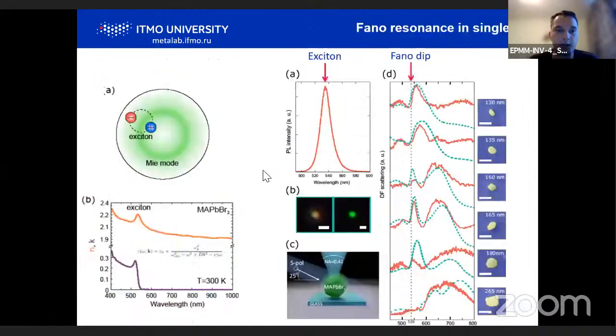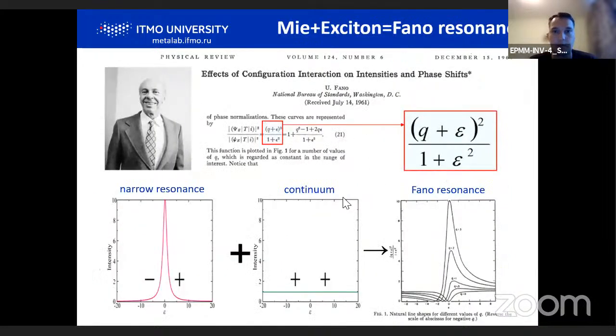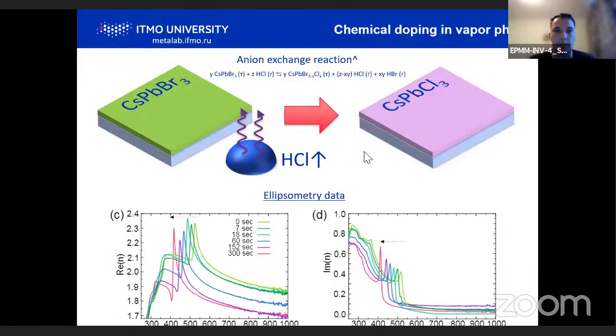Also, fundamentally, it's interesting to see what is going on when we couple excitonic state with Mie resonances. And according to our measurements and calculations, we observe that coupling of Mie resonance and exciton always results in some minimum in scattering spectra. And this minimum is due to Fano resonance when we overlap narrow exciton and relatively broadband Mie resonances. We always have Fano-shaped resonances in this case. But the question is, can we tune such kind of resonances, and how strongly can we tune it?